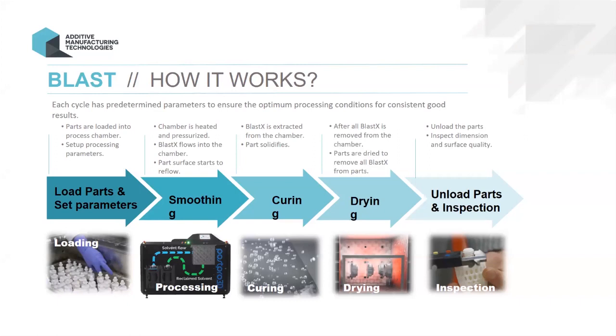So the parts go into the chamber, and the liquid chemical is vaporized. The vapors are introduced into the chamber, and as soon as those vapors touch the parts, they start working and dissolving the surface of the polymers. All those partially fused particles that you saw on those micrographs, we dissolve them and reflow them, without changing the dimensions of the part.